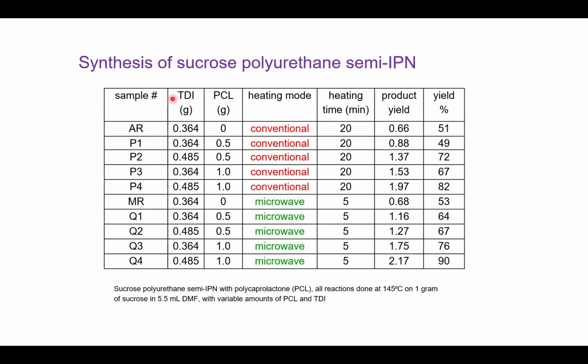We take TDI together with the sucrose, and we just add the polycaprolactone on top of it. So they are polymerized together. As the TDI and the sucrose form a polymer, it encapsulates or entangles the polycaprolactone as a second polymer, and you form basically an intimate blend. And so this will be 2 levels of TDI, 2 levels of polycaprolactone.